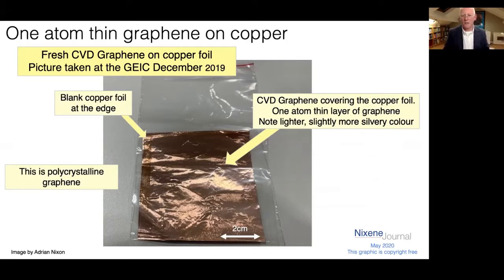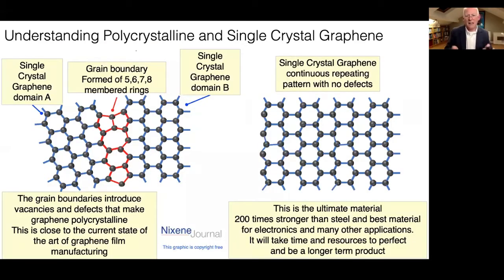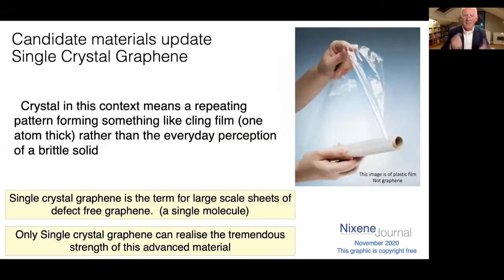This is polycrystalline graphene. This is what it looks like. Single crystal graphene on the right-hand side is this perfect sheet of material with no defects. On the left-hand side, the red lines I've highlighted show where two crystal boundaries have grown together, and there's discontinuities. There's also defects and vacancies there, and these reduce the strength. Now, on the left-hand side, that's where the current manufacturing state of the art is. On the right-hand side, this is where it's headed towards. So all the stuff I'm going to show you in a minute is making polycrystalline graphene, not single crystal graphene. And you can think of single crystal graphene looking a little bit like cling film, you know, you get on a roll. A crystal in this context means a repeating pattern.